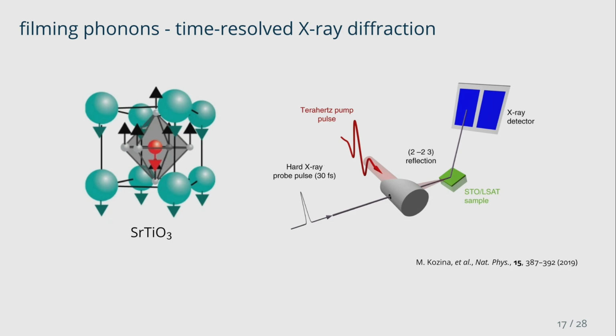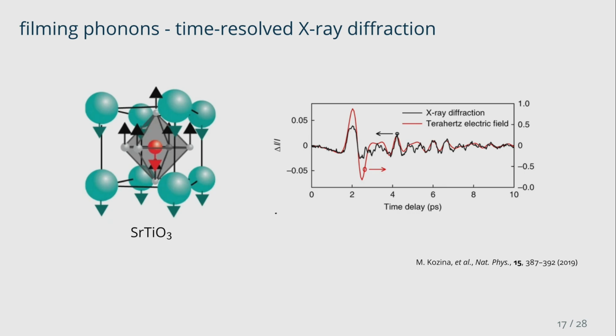But now they do this time resolved, and on a crazy time scale. Basically, every 30 femtoseconds they have a pulse, so every 30 femtoseconds they can read out what the actual crystal structure is by now. If they do this experiment for strontium titanate, they can measure exactly what we are studying: the motion of this phonon mode. You see it oscillates a bit like in the picture that I showed at the beginning. But you can also see that there's a lot of noise, so obviously there's some stochastic process involved. That underlines the claim that stochastic thermodynamics might be a very good framework to study this.